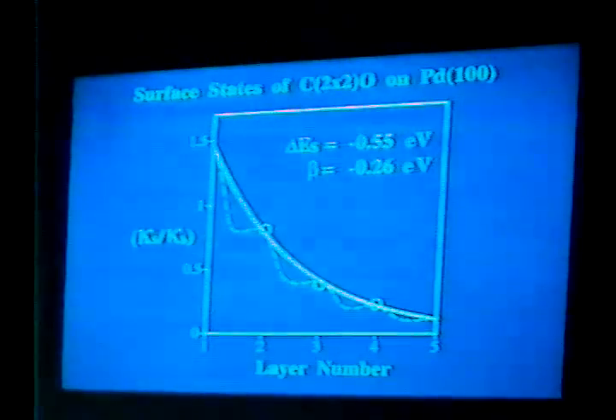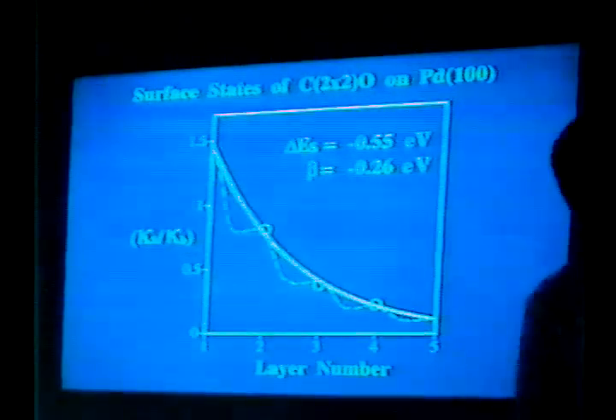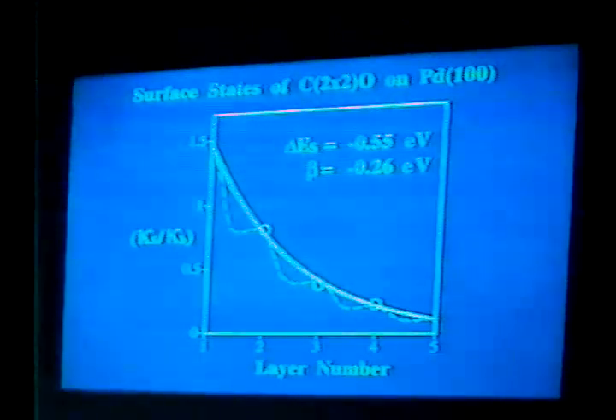There is in fact a theory of surface states that says that this is exactly what ought to happen. I have used a schematic model here by Davison and Levine that was published in the 1960s, where I have used their theory to determine some of the parameters of this surface state. It's a surface state that decays like here. This is a picture really of the wave function, but it is a single energy. That surface state is a single energy shifted by 0.55 eV with respect to the bulk state.